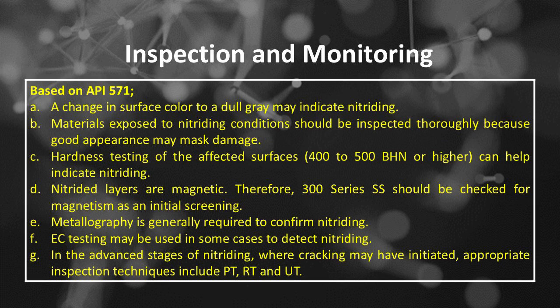Nitriding damage inspection and monitoring based on API 571. Number A, a change in surface color to a dull gray may indicate nitriding. Number B, materials exposed to nitriding conditions should be inspected thoroughly because good appearance may mask damage. Number C, hardness testing of the affected surfaces, 400 to 500 BHN or higher, can help indicate nitriding. Number D, nitride layers are magnetic. Therefore, 300 series SS should be checked for magnetism as an initial screening.